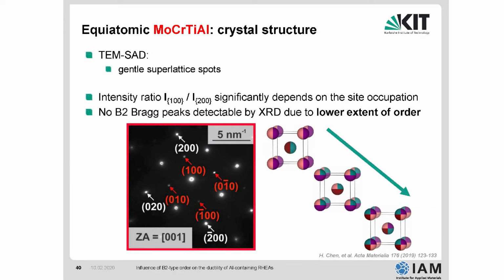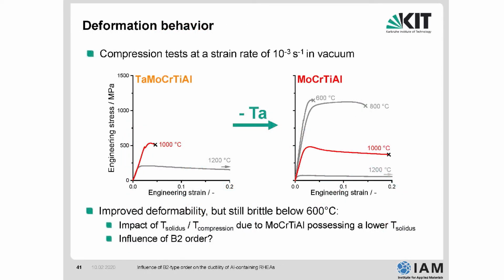So there must be ordering, meaning there's no randomness again in the atomic site occupancy. It's preferred atomic site occupations. So this is the B2 structure, right? A center atom and simple cubic structure. Now, again, the test without tantalum, no Laves phase, the material should be ductile, right? Well, it's better than it was before, so we could obtain 800 C tests and 600 C, but again, below 600 degrees C, we did not see any ductility in the stress-strain curves.